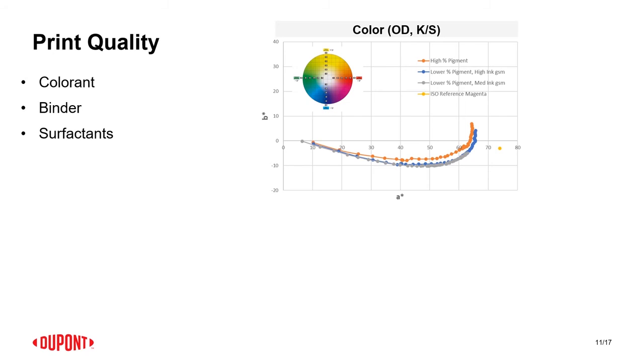And so it turned out that actually stepping back on the pigment loading was a better thing for this particular ink formulation, because it gave you a much cleaner magenta that was repeatable despite the amount of print density that you had. But at the end of the day, that was actually the thing that made the color look the best, not just aiming for maximizing the amount of pigment, right? So again, it's always this balancing act and understanding what affects the performance you're looking at.